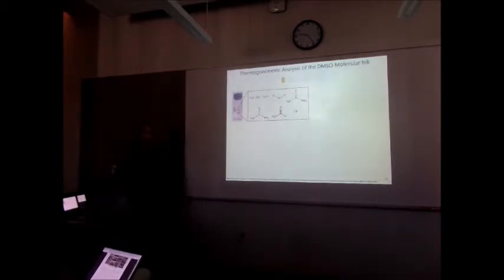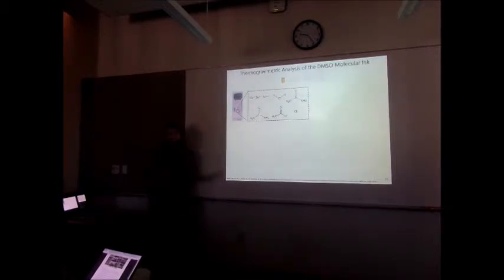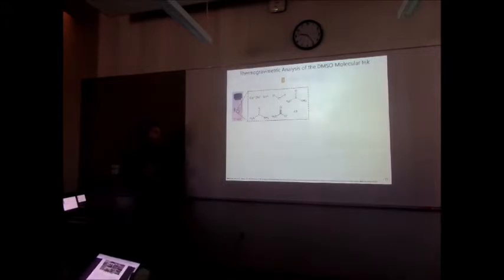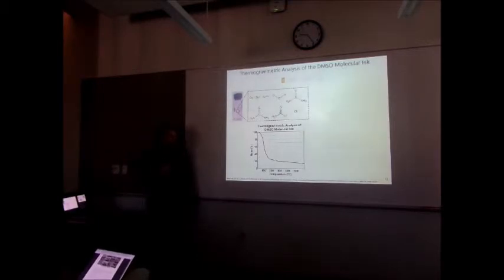So moving on to the first step, the ink in this process, we have these different constituents in the molecular ink. We have DMSO, we have thiourea. These Lewis basic compounds complex with the Lewis acidic metal chlorides in solution, and acetates in some cases. And if you look at thermogravimetric analysis of the molecular ink, this is looking at the mass loss over time as you increase the temperature of the ink.